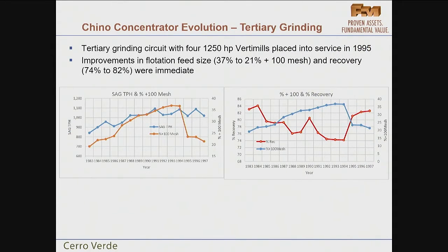So, moving along quickly, here you see the installation of the Verti mills in 1995. Magically, there's a drop in the flotation feed size, an immediate drop from 37 to 20-ish, 22. And the recovery improved from 74 to 82-ish. So, magic. I wonder if there's a relationship.